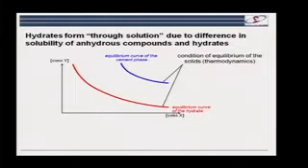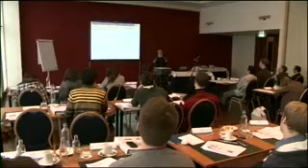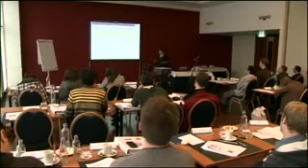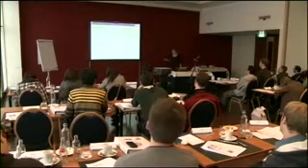But then we get something different happening, because the ionic species can get together in different combinations and precipitate new compounds. Okay? So that's what I'm trying to show on this slide: the solubility of the cement phases is much higher than the solubility of the hydrates. And it's this difference in solubility that drives the hydration reaction. It's a thermodynamic process.